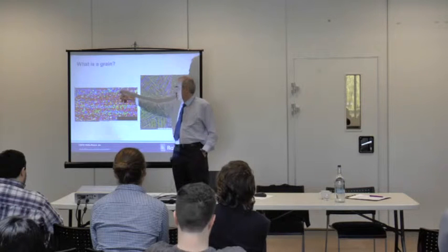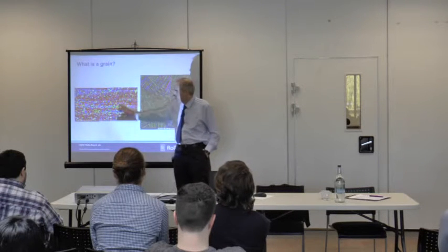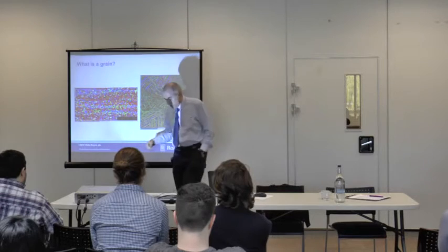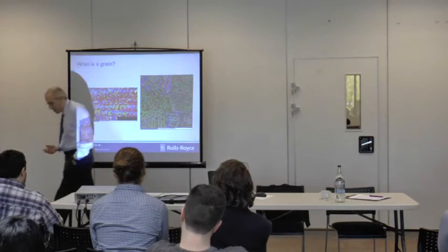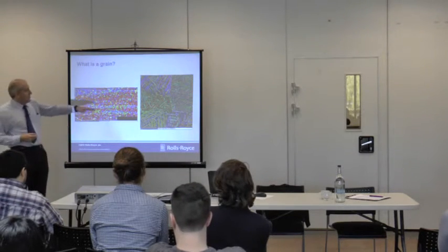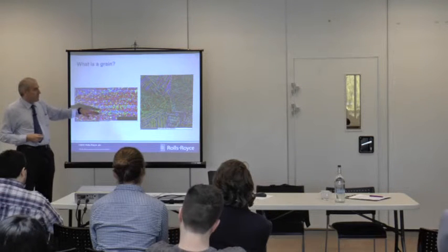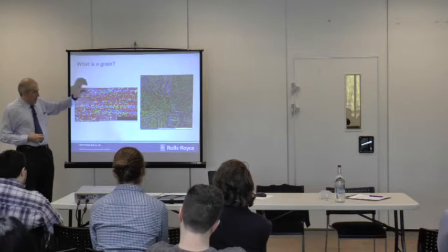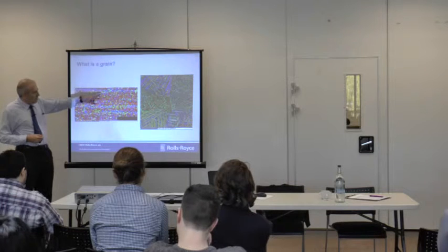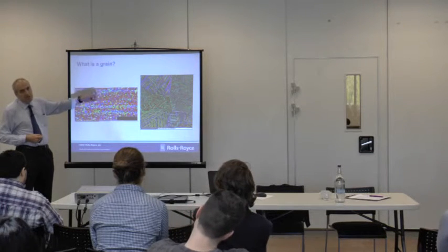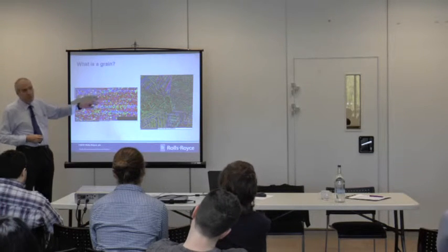The other thing I want to get across to you is that in this one, you'll see that you've got little blobs, and you've also got bands of colour. And these actually correspond to crystallographic texture evolution when you process materials. So effectively here, we've got a composite on many different length scales. And the really neat thing is that what it chooses to recognise as a significant microstructural feature depends on the load